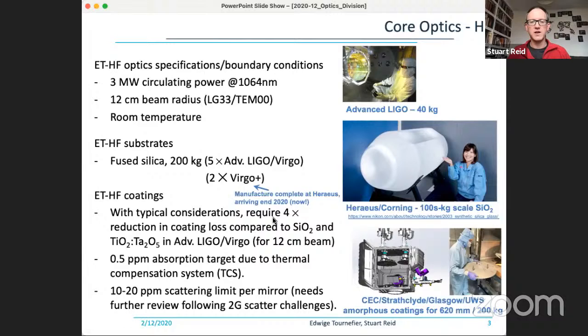Coatings, we require a 4 times reduction in the coating mechanical loss compared to the current Advanced LIGO, Advanced Virgo coatings. This isn't really a precise number, because we also need to take into account the optical properties. So if we're using coatings of the same optical properties in terms of refractive index, then this is true, but of course it will change if we change to other materials. But broadly speaking, we're looking at a 4 times reduction.